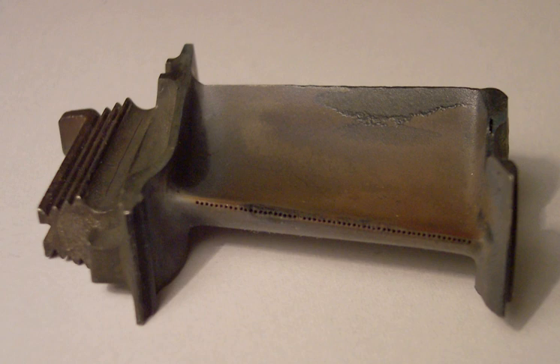Thermal barrier coatings (TBCs) are used extensively on the surface of superalloys in both commercial and military gas turbine engines to increase component life and engine performance. A coating of about 100 to 200 micrometers can reduce the temperature at the superalloy surface by up to 200 K. TBCs are really a system of coatings consisting of a bond coat, a thermally grown oxide (TGO), and a thermally insulating ceramic top coat.